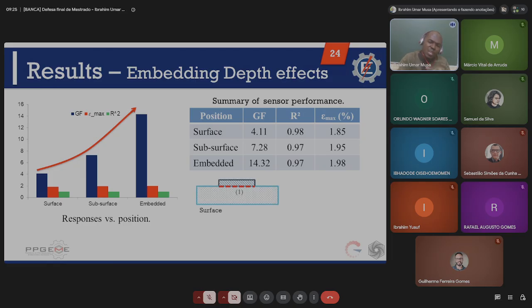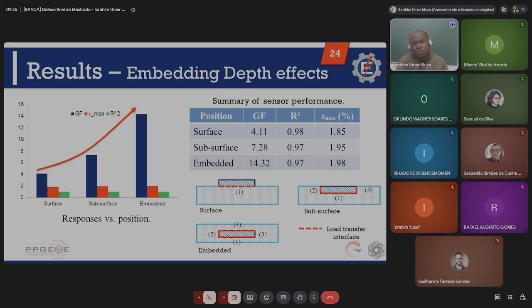And this behavior of the sensitivity to the geometry could be attributed to the load transfer interface. Remember the load transfer interface, because for the surface integrated geometry, we only had 1 load transfer interface. For the subsurface design, we have up to 3, and for the fully embedded, as we can see, we have up to 4 different load transfer interfaces. This is per 1 sensor trace. And we conclude by saying that embedding, even though it appears to be simple, is a very powerful tool for tuning the sensitivity of the sensors.